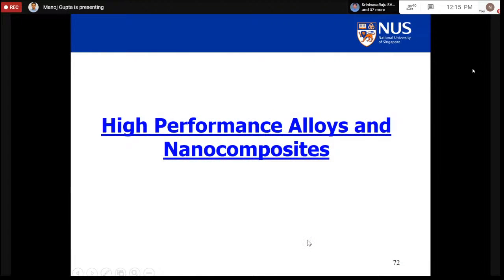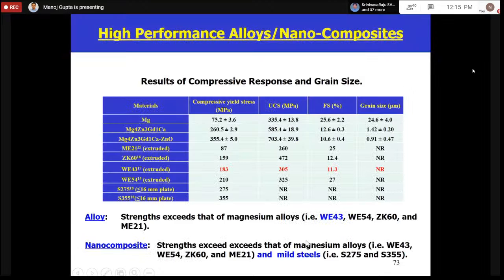In the development of the alloys, we developed alloys containing zinc, gadolinium, and calcium, and you see the improvement in the properties by almost 3 to 4 times, from 75 to 260 megapascal, 335 to 585 megapascal. In this case, your failure strain reduces but stays beyond 10%, which is a critical requirement of a manufacturing engineer.